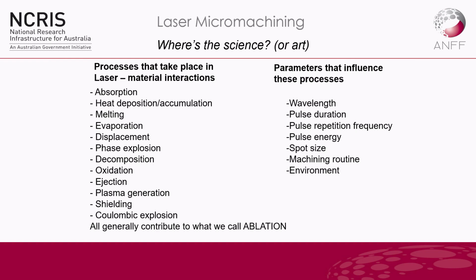That's when the material changes state in a very explosive way. So it goes from solid to gaseous very quickly, and essentially gas needs to take up a lot more volume than the solid material does, and so the material ejects itself away from the surface. And then you have other things going on, like the plasma generation, shielding of the incoming laser light by that plasma. And when we get to really short pulses, we can have a phenomenon called coulombic explosion.